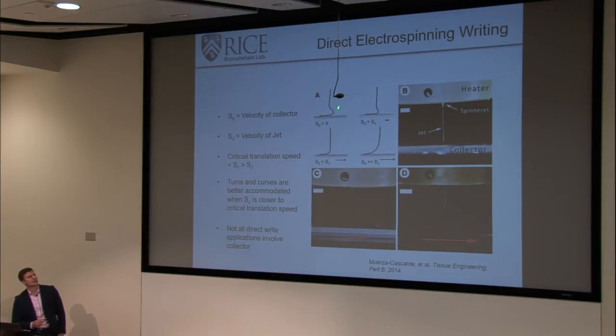If you've got a stationary collector, you get this heel that you produce with the fibers. This is something that you see on extrusion printers as well, but generally this error isn't as obvious as it is in electrospinning since you work with much finer fibers. So what we call the critical velocity or the critical translation speed here is when the speed of our collector is slightly increased compared to the speed of the jet itself. And if we can do that, we can start to achieve more uniform fiber deposits, which will produce more predictable fibers on our scaffold.